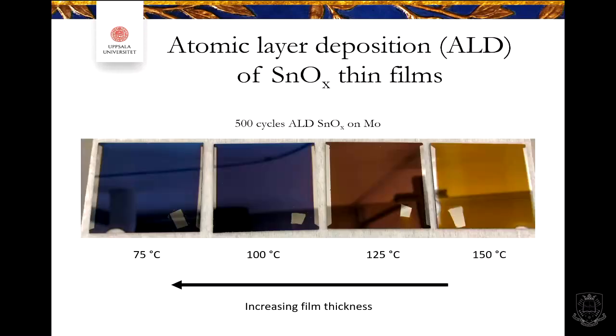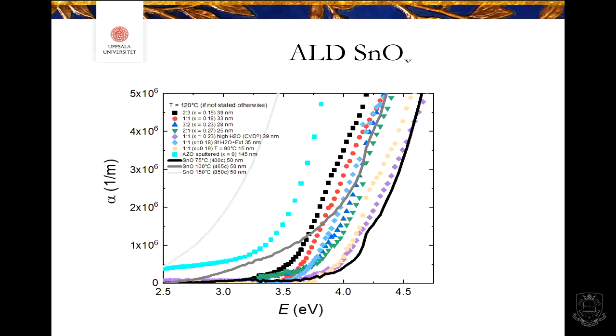Another thing we have looked at is atomic layer deposition of tin oxide. Here we have tested different temperatures and how that affects the technique of atomic layer deposition. What happens with the thickness if you increase the temperature during your deposition? We don't need to look at all the curves here, but we can take a look at the last three, these ones. Here you see different temperatures. We have tried to keep the thickness constant, and this is how many cycles are needed, where atom layer by atom layer increases the thickness. So you repeat it many times, like cycles like this, and then you get the thickness in the end.